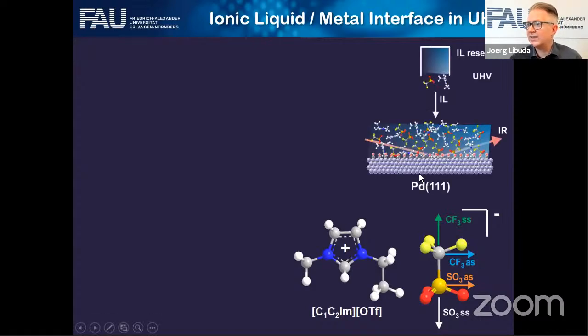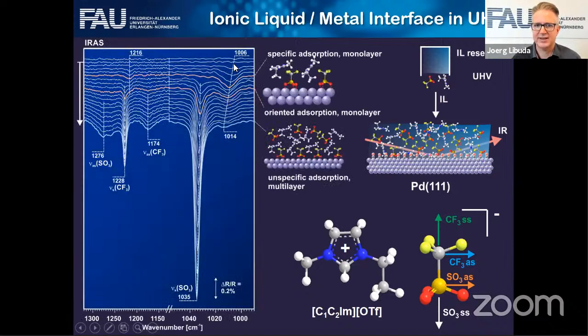And we can understand how it interacts with the metal surface. We adsorb it on the metal surface and do a surface science experiment in which we do infrared spectroscopy in order to understand what the interaction is. Here we grow this layer. These are spectra taken while we grow this layer. And in this layer, we can identify specific peaks that tell us that in particular, this OTf ion adsorbs on the metal surface via the SO3 group. So this is the thing that really sticks to the surface. That's, of course, under surface science conditions.